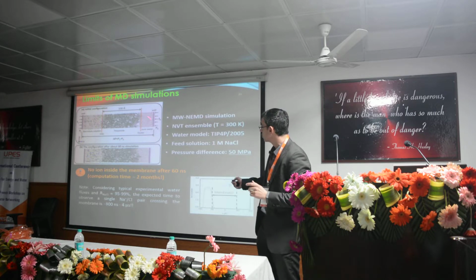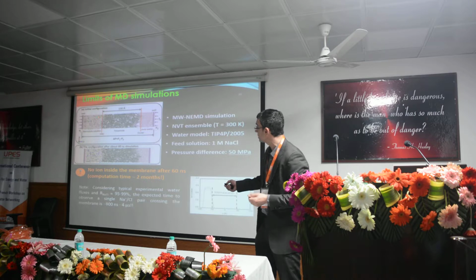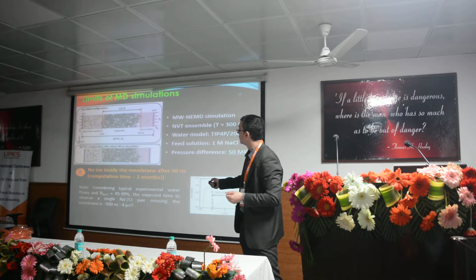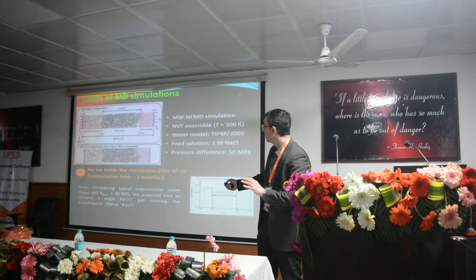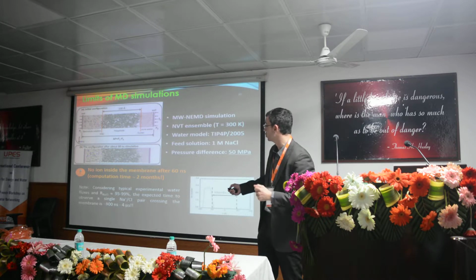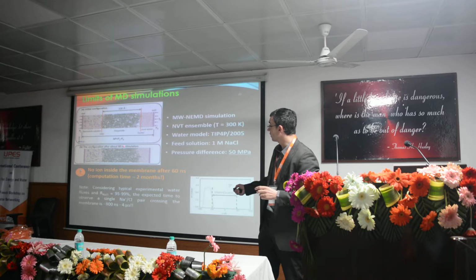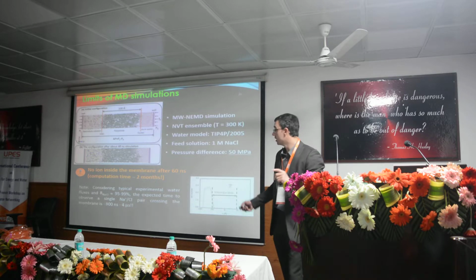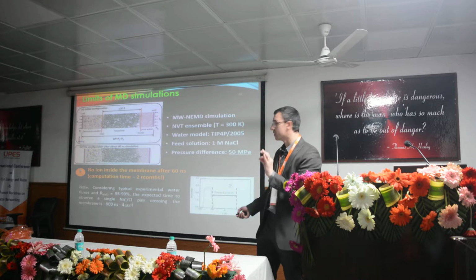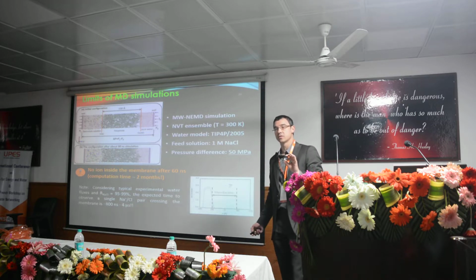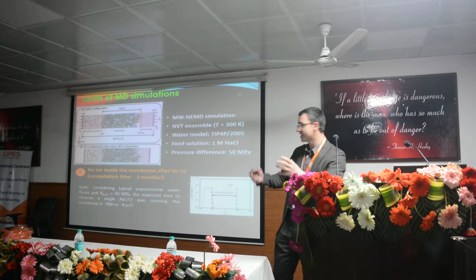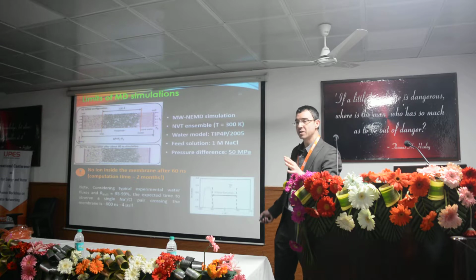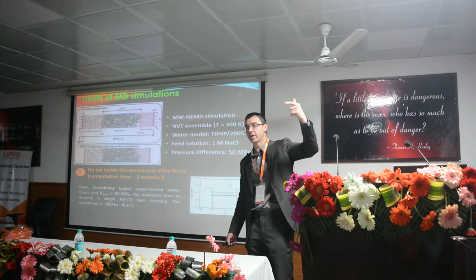This snapshot shows the initial configuration of the system with all ions. They are shown by the blue and the green balls here. All ions are located, of course, on the same side of the membrane, and then we push onto the left wall, okay, to filtrate the solution. And this is the snapshot after 60 nanoseconds of simulation. You can see that not even a single ion entered the membrane after 60 nanoseconds of simulation. To give you an idea, for a system of this size, 60 nanoseconds represents approximately 2 months of calculation with multi-parallel computers.